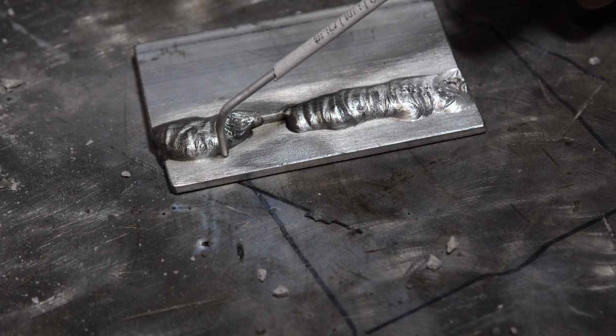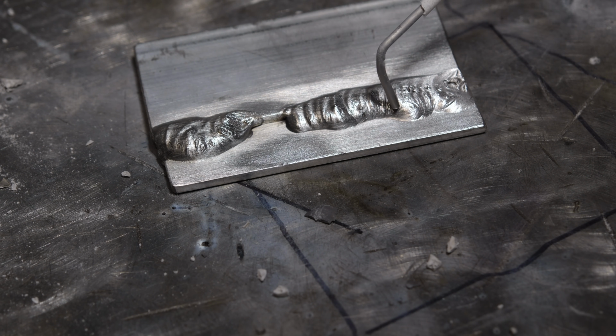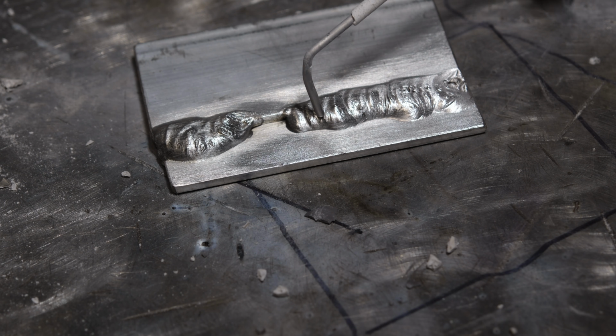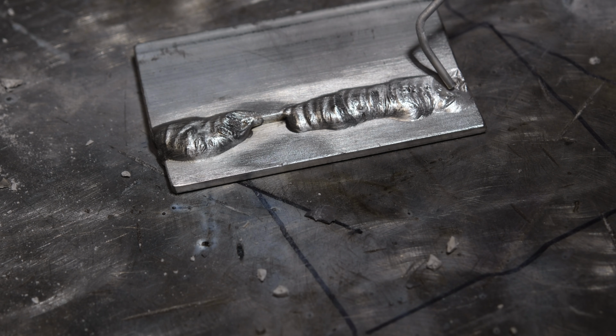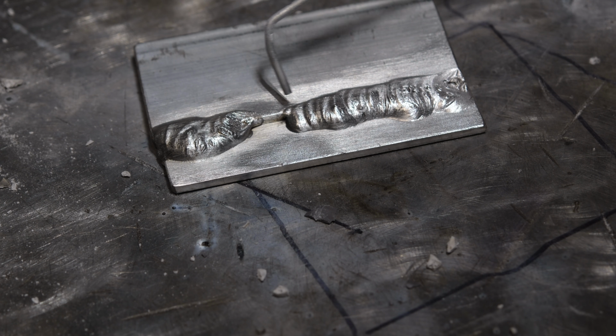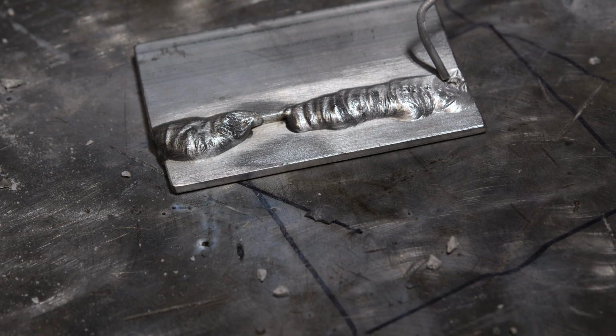So it's very common to get cold lap when you're welding over this stuff with argon because it's more or less sticking to that oxide layer and not melting into the base material. So realistically, this weld might get you off a trail somewhere or out of the mountains of Afghanistan, but under no circumstances would I ever trust this to actually last. Anything experiencing vibration or shock loads, this will fail, I guarantee you. However, this might get you out of a bad spot, so can you do it? Yes. Should you do it?